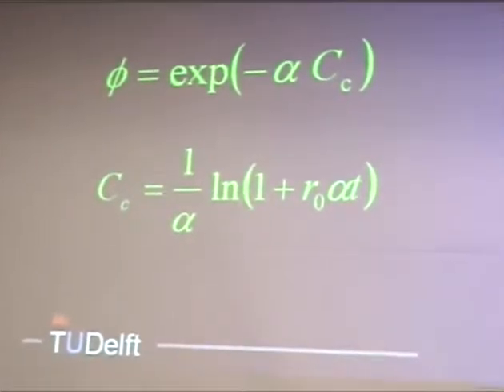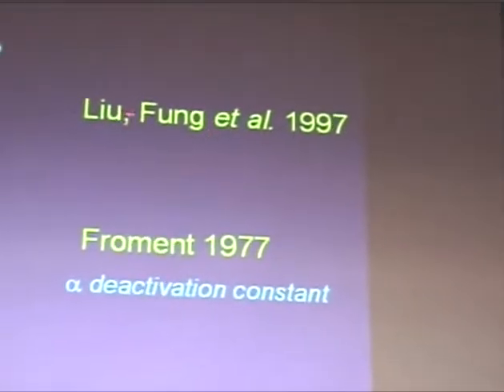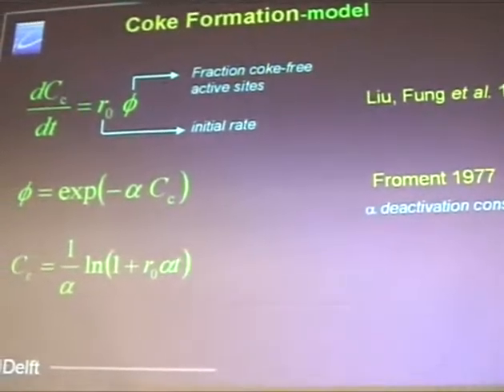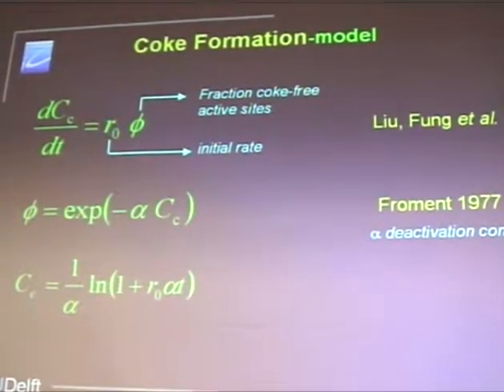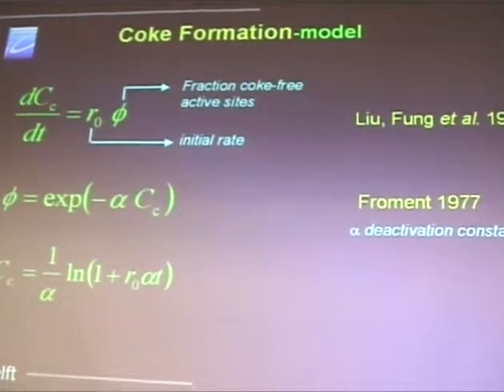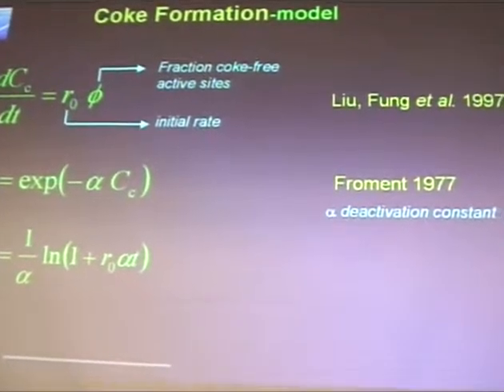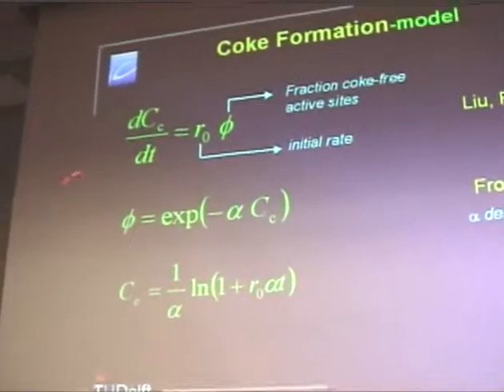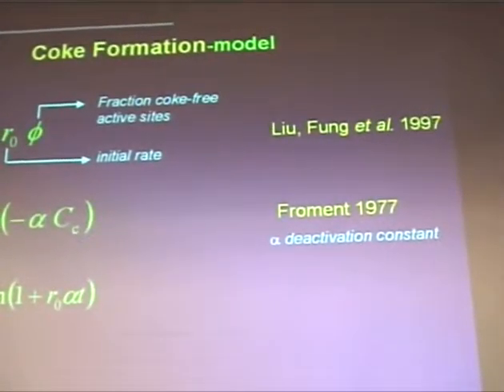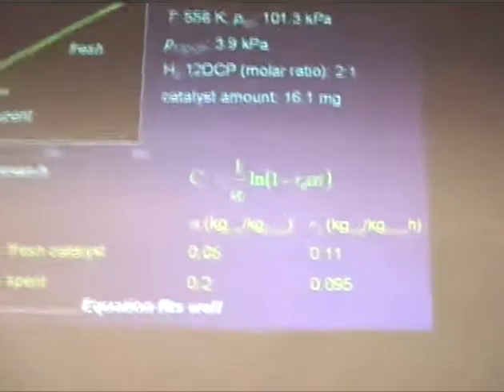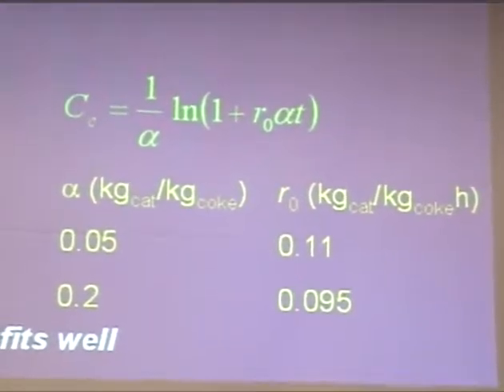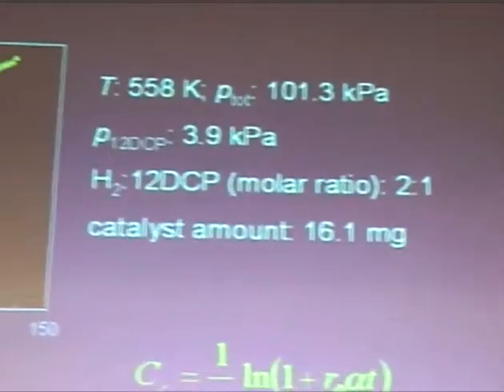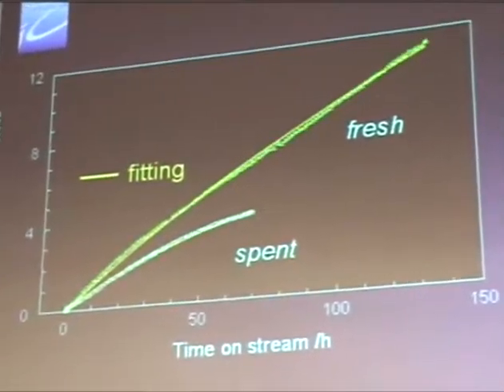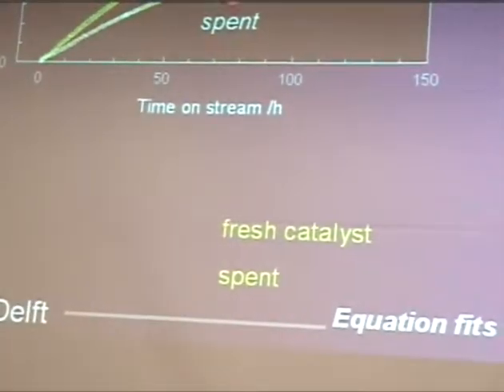For the model, I use basically the work that has been pioneered by Froment, and also in a newer group that has been done. And in that case, by a simple exponential function for the deactivation function, you come to an expression. You can debate the interpretation of it, but as people often notice, with noble metals this works quite well. And here then the fits, you see here the spent and fresh catalyst. The spent catalyst, of course, has a lower coking activity. It should, of course, because it has been deactivated.